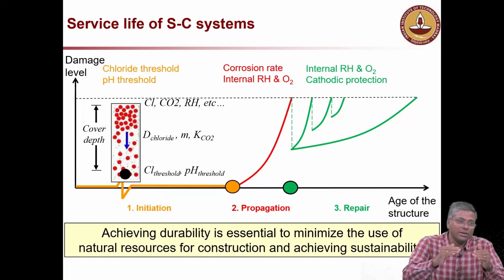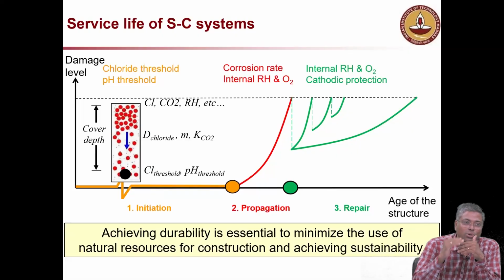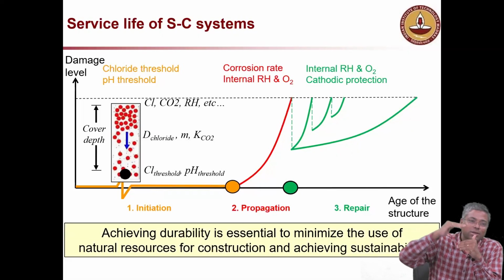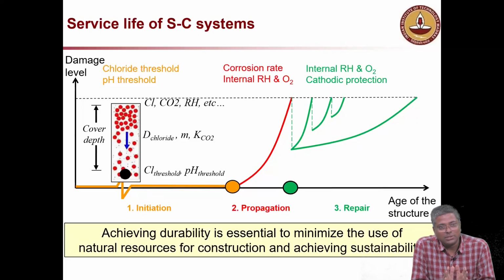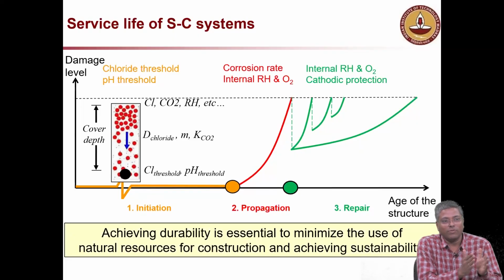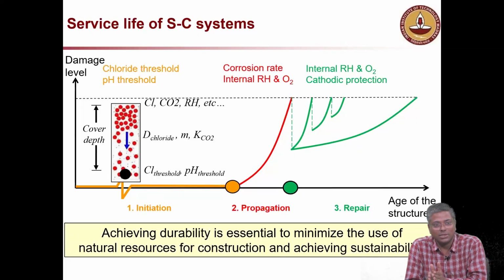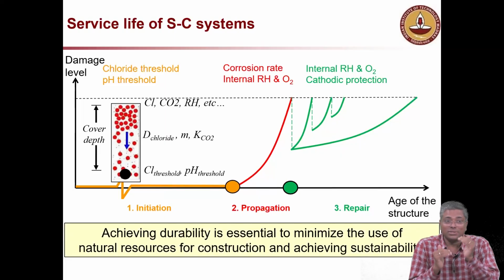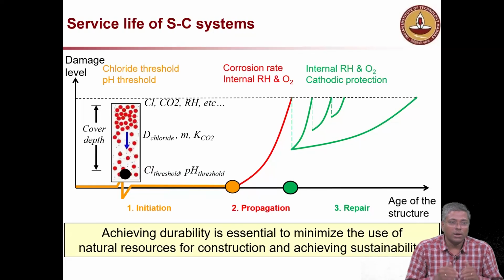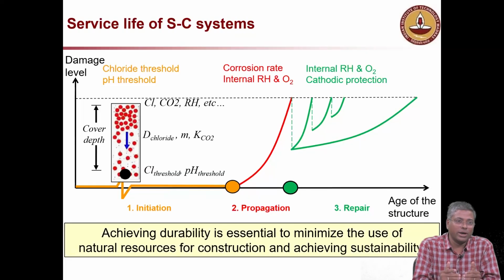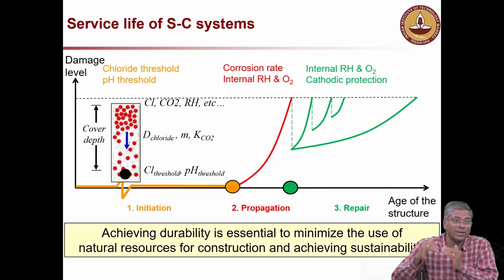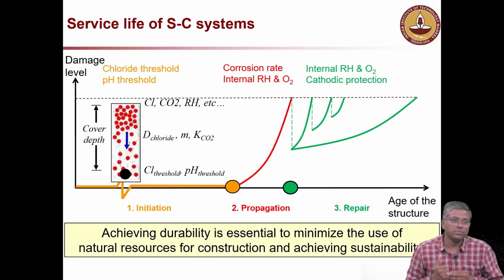So they are selling steel saying that it is corrosion resistant steel, because we did some studies on the chloride threshold of corrosion resistant steel and other steel. We couldn't see much advantage, but the corrosion rate is low. But my concern is more about chloride threshold or pH threshold than the corrosion rate. So you're actually spending more money on corrosion resistant steel.